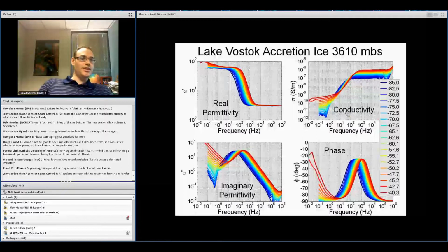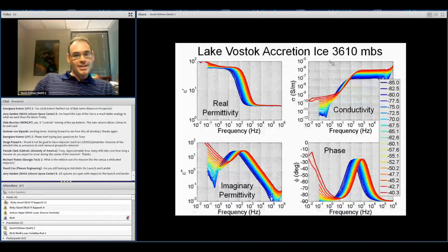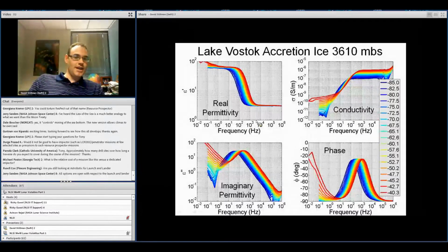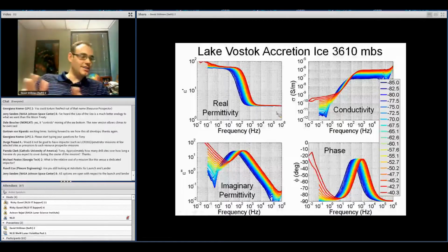So this is an example of some data. This is from a sample from Lake Vostok, the accretion ice right above it. You'll see four plots here, and I'll be showing these a lot. We've got permittivity on the left side, real and imaginary, top and bottom, and then the conductivity and the phase. The colors indicate the temperature in degrees C. The warmest will always be in red. What you see here is a great frequency dependence in the dielectric properties, and this is the signal we're looking for to map this in the ground using geophysics.